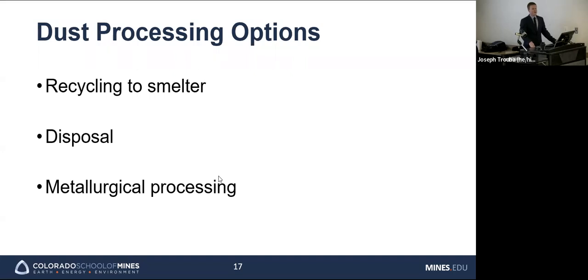So what are the options for processing dust? Dust needs to be processed because it contains a substantial amount of copper. However, there are impurities in dust that can lead to a buildup of negative elements. If dust is directly recycled to the smelter, as is often done, it leads to a buildup of particularly bismuth, which is deleterious, or has negative effects, during copper electrorefining. Its electrochemical potential is close to that of copper, and it's a severe impurity in cathodes because it negatively impacts conductivity. It severely negatively impacts the conductivity of copper, and as we all know, copper is the conductive material.